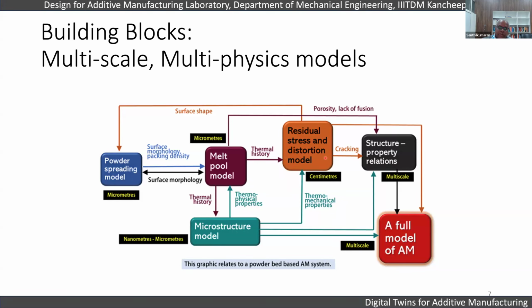And then you also use the same thermal history to predict the residual stress and distortion. And also thermomechanical properties come from the microstructure model because the evolution of the properties is controlled by the evolution of the microstructure. This is typically in the mesoscale, in centimeters, where the residual stresses happen. And structure property relations like cracking, porosity, and lack of fusion can also be determined from the melt pool model. Like you can get the porosity values and lack of fusion from heat. And that could be used to understand the complete linkage of the process, structure, property, function, behavior mapping. So that could become a full-scale model. So this is what we call multi-scale and multi-physics model. Now, when I say multi-physics, we need to go deeper into the process to see what are the multi-physics involved in a typical PBF process.